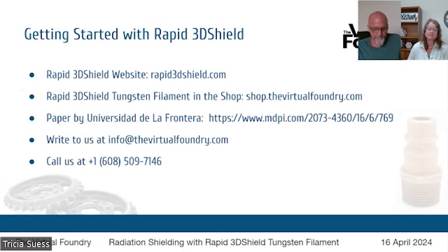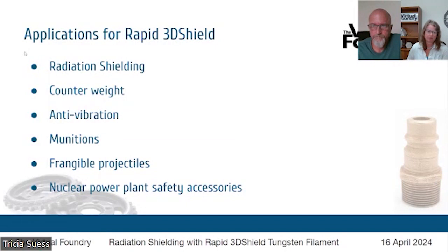Yes, can you hear me? Yes. Hi, good morning. So I'm a health physicist at Bruce Power. We use it for a custom solution as opposed to using our lead blankets, which are 1 foot by 3 foot, and they're about 33 pounds each. So instead of using, let's say, 3 lead blankets at 100 pounds on something, we can replace it with our shielding designs, which are roughly oval pill shaped things, maybe 2 to 4 centimeters thick, between half a kilogram and, I think the biggest one we've printed so far is almost 4 kilograms.